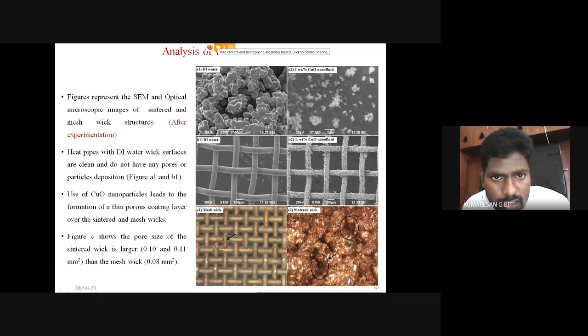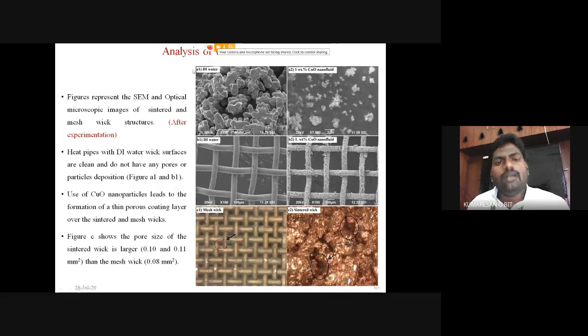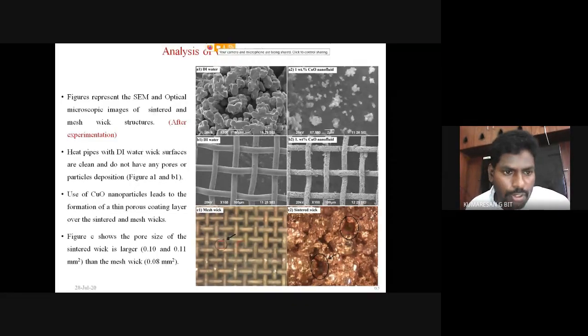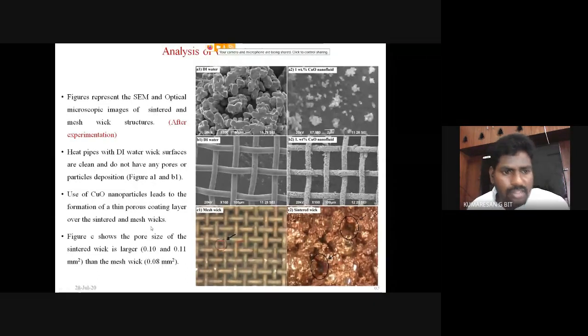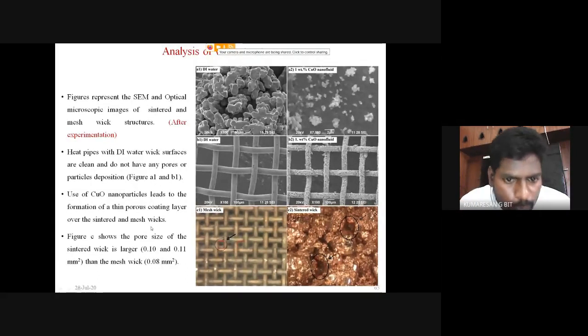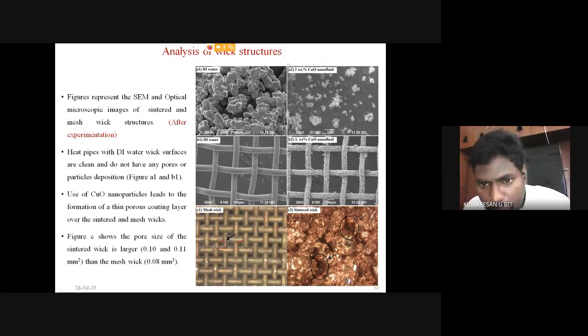So this first A1, B1 and C1 images are taken from the heat pipe filled with the DI water, and the second A2, B2, C2 images are taken from the heat pipe which is filled with the nanofluids. With DI water, the wick surfaces are clean and do not have any pores over the surface. But the use of CuO nanoparticles leads to the formation of a thin porous coating layer. You see in the B2 image.